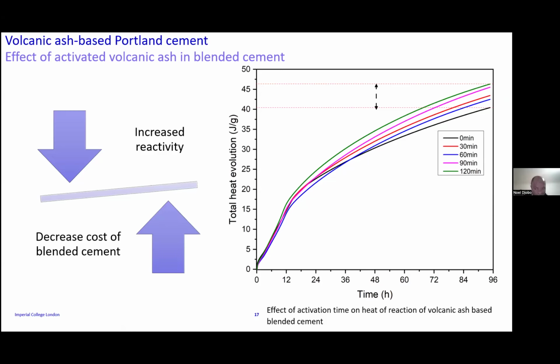So the direct impact is mainly the decrease of the cost of the blended cement. As I said, cement is the most carbon intensive and the most expensive part in blended cement. So when you substitute cement with volcanic ash, for sure you decrease the cost of the cement, which makes sense, and you also improve the properties. By doing the mechanochemical activation, we have been able to achieve this, which is quite interesting for Africa, where the cost of cement is more expensive. Cement is more expensive in Africa than in Europe, whereas the purchasing power in Africa is by far lower than in Europe or North America.